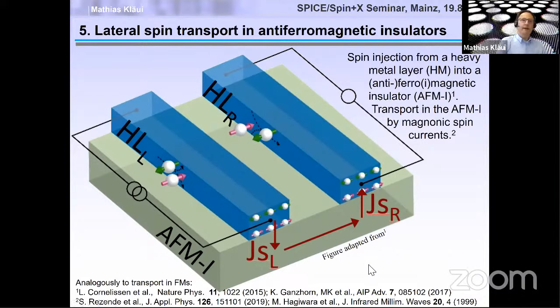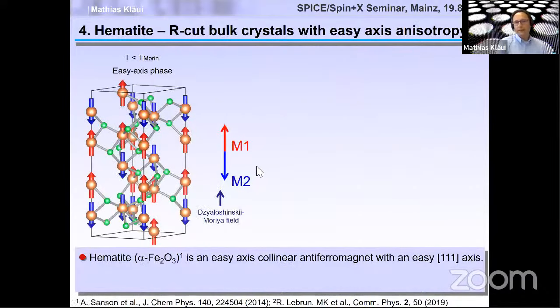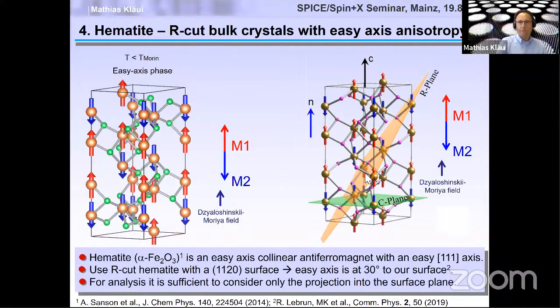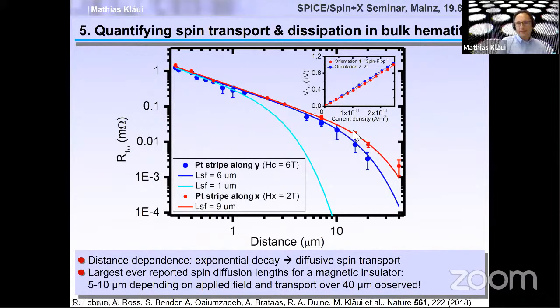And so what we have chosen as an antiferromagnet is hematite, which is an easy axis antiferromagnet below the Morin transition, and an easy plane weak ferromagnet above the Morin transition. And we investigate different C-plane and R-plane surfaces and put our platinum strips on top of these surfaces. So the first thing we found in this paper 2 years ago that stirred a bit of interest was that actually the distance dependence of our transport signal shows that we can get transport over long distance, over micron distances. And this was novel at the time because so far people had seen only transport over the distance of a few nanometers. So here we're talking about 40 microns of transport distance.